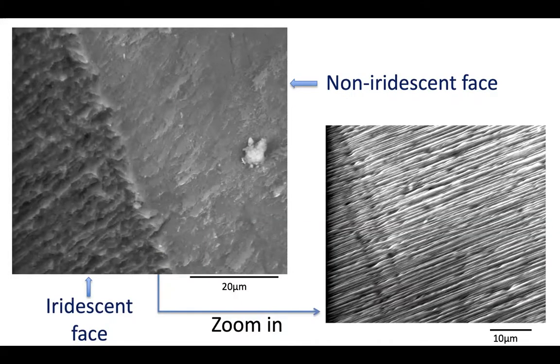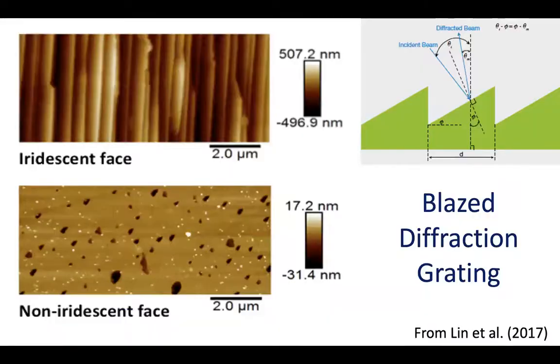So Sunny Lin, again, my graduate student in gemology, decided to look at these prismatic quartz crystals with a scanning electron microscope. And on the left, what you're looking at is that boundary between an iridescent face and a non-iridescent face. And very consistently, the non-iridescent faces are just flat, but the iridescent faces actually show this kind of ridge and valley texture. And when we zoom in at higher magnifications, this kind of diffraction grating within the crystal becomes immediately apparent. So as soon as we saw this texture, we knew immediately this had to be responsible for the iridescence. Sunny took her samples again to the materials characterization laboratory, looked at them with atomic force microscopy, and kind of reproduced what we saw with the SEM.